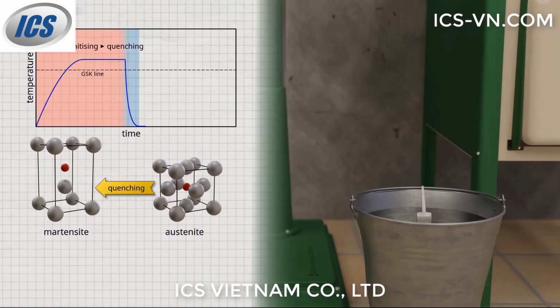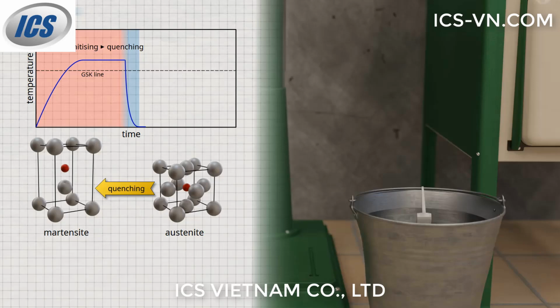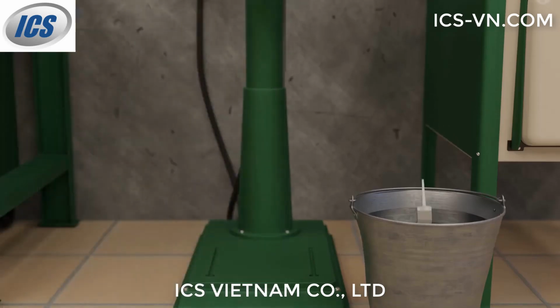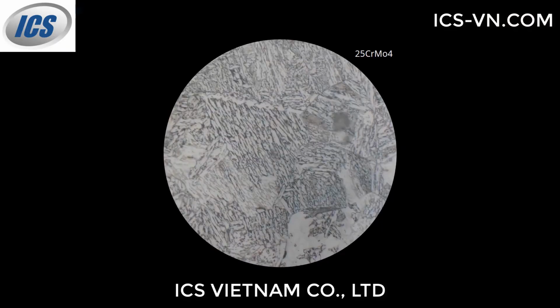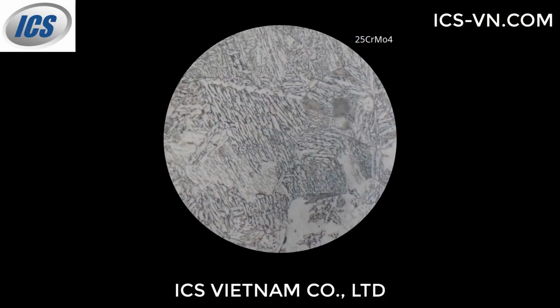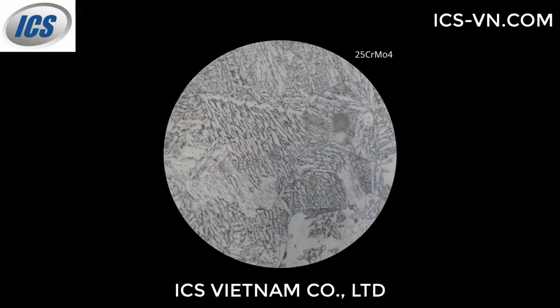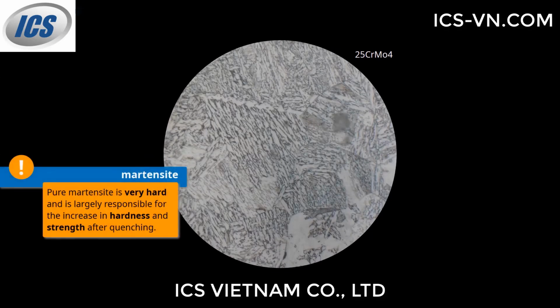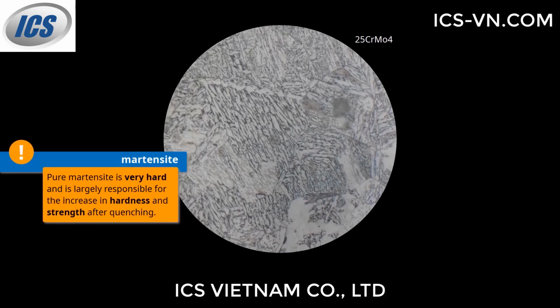The tetragonally expanded lattice structure ultimately represents a new microstructure, which is called martensite. Under the microscope, martensite is recognizable as a needle-like or plate-like microstructure. So note, pure martensite is very hard and is largely responsible for the increase in hardness and strength after quenching.